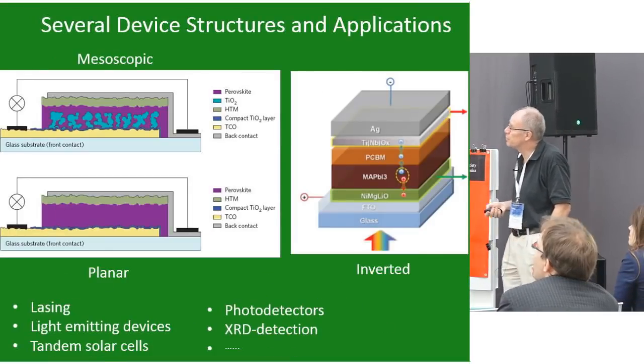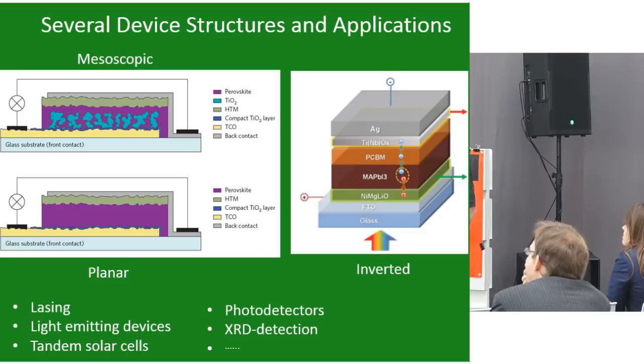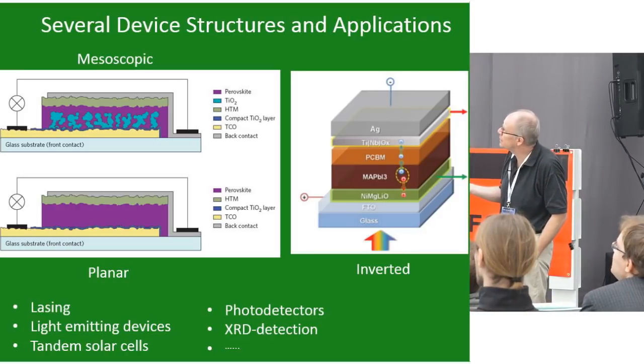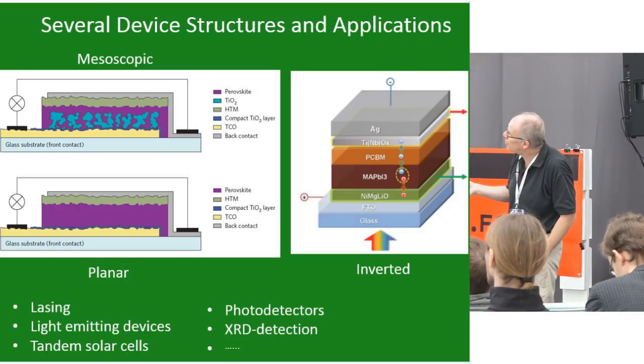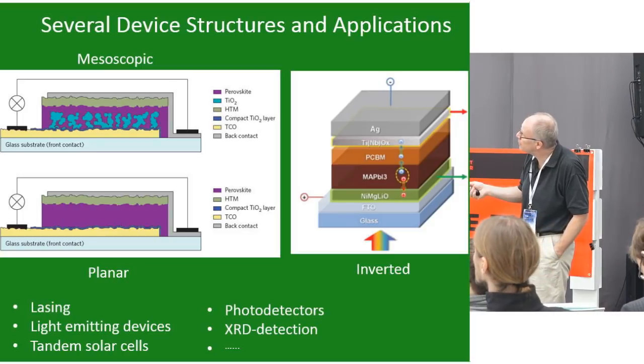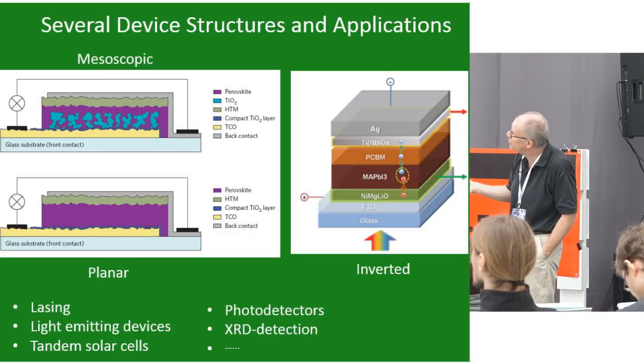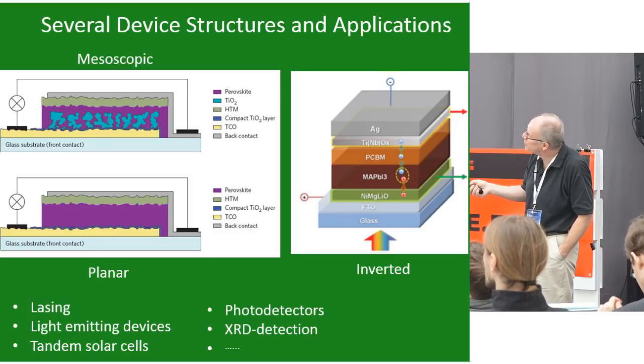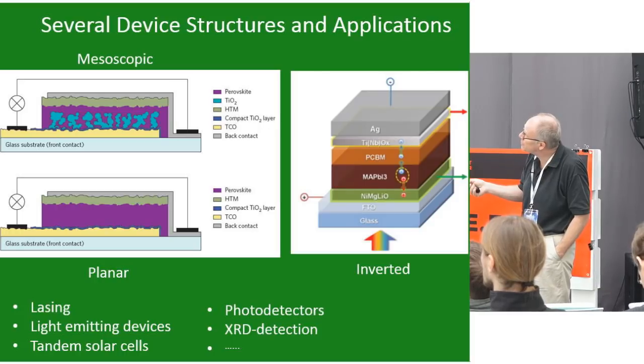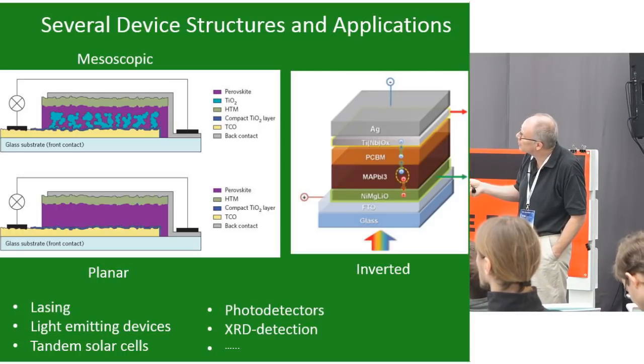There are also different possibilities for device structures. This is the mesoscopic, dye-sensitized cells. It's the TiO2 particles here impregnated in the perovskite absorber film. Typically now the TiO2 layer is 200 nanometers and the perovskite is half a micron.